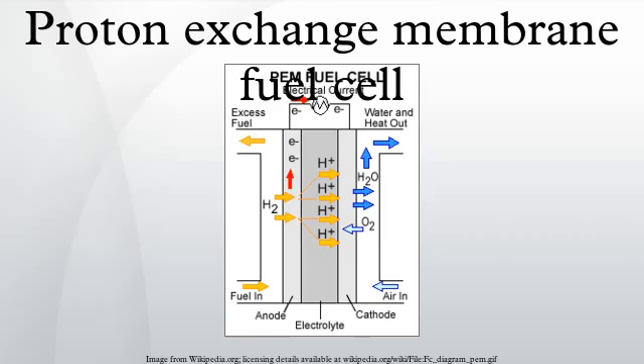Further efficiencies can be realized using an ultrasonic nozzle to apply the platinum catalyst to the electrolyte layer or to carbon paper under atmospheric conditions, resulting in a high-efficiency spray. Studies have shown that, due to the uniform size of the droplets created by this type of spray, the high transfer efficiency of the technology, the non-clogging nature of the nozzle, and the fact that the ultrasonic energy deagglomerates the suspension just before atomization, fuel cell MEAs manufactured this way have a greater homogeneity in the final MEA, and the gas flow through the cell is more uniform, maximizing the efficiency of the platinum in the MEA.